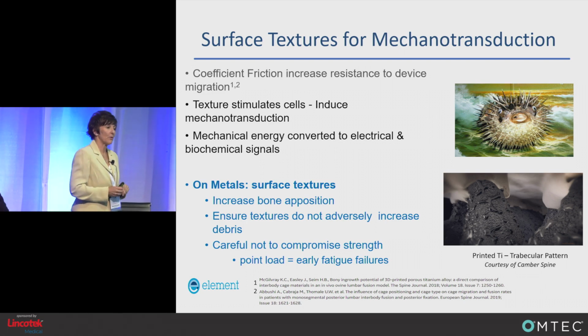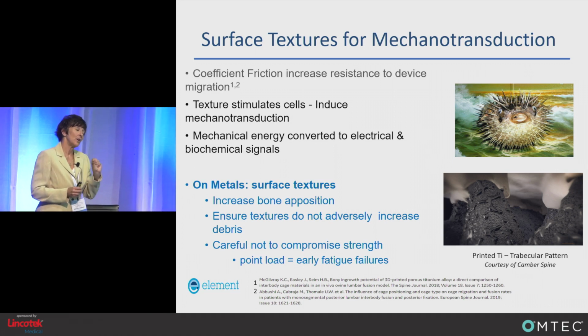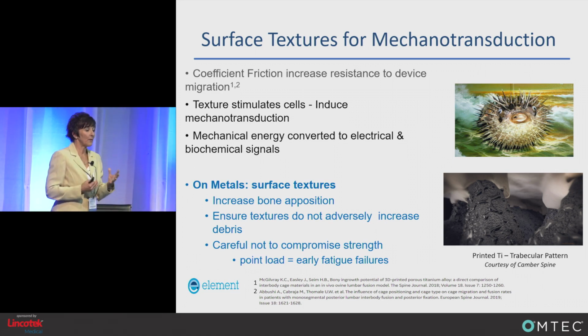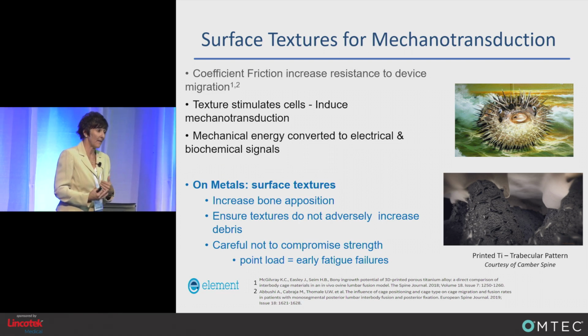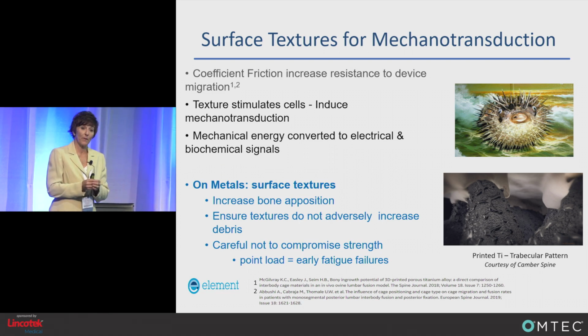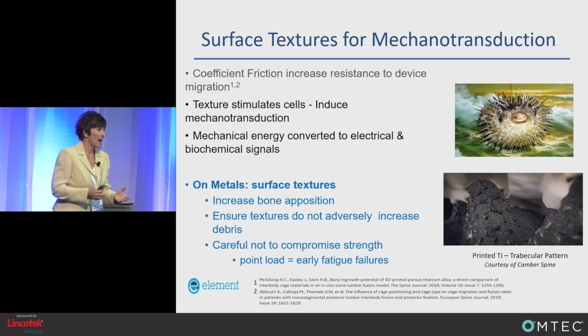Rough surfaces are great, but during a test, you can also get point loading because a lot of these surfaces are not consistent with their peaks and valleys. So sometimes you may have a point load, and that's more artifactual. You have to make sure you understand, okay, we had a fatigue failure. It's just like having a notch fatigue in a piece of titanium. Is it real or is it an artifact?